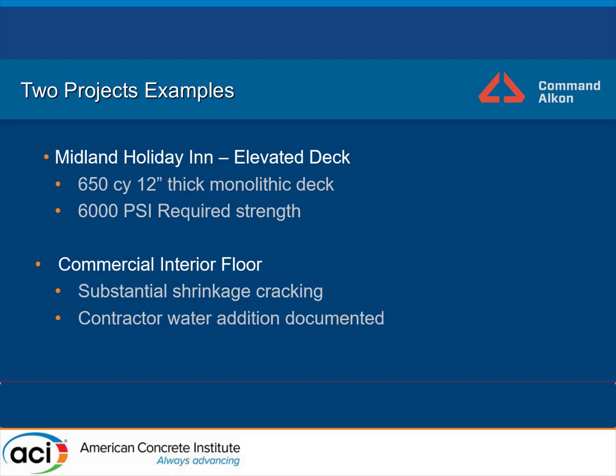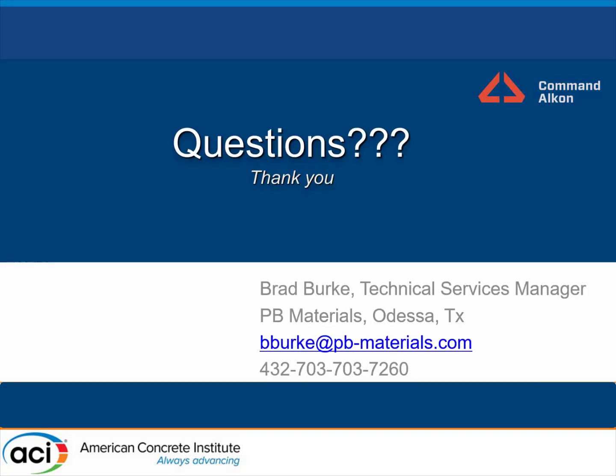And we came up with that report. 20 gallons, 30 gallons. One load had 70 gallons of water documented on a 10-yard load used by his crew. I showed him that. We didn't have to have another conversation. So it's very powerful to have the documentation this tool gives us. Those are the 2 success stories I thought I'd give you.